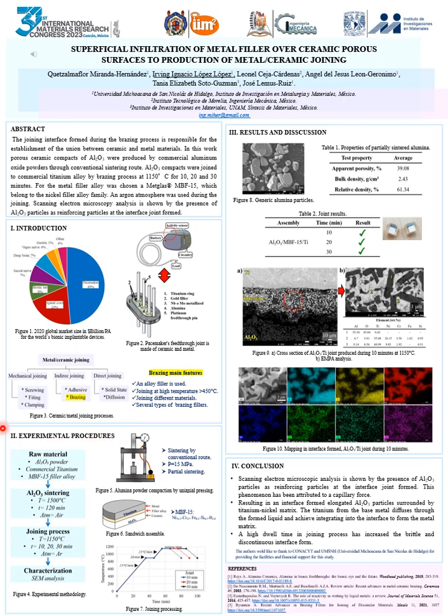Experimental procedures. The raw materials utilized were commercial aluminum oxide powder, used to produce ceramic compacts, high-purity commercial titanium alloy 99.7%, and a metal sheet composed of nickel, chromium, iron, silicon and boron. This filler alloy corresponds to the MBF15 series family. Generic-grade aluminum oxide powder was selected to be sintered by the conventional sintering route. The aluminum oxide powders were pressed at 15 megapascals by uniaxial pressing. After that, the aluminum oxide green compacts were sintered at 1500 degrees Celsius for 2 hours.